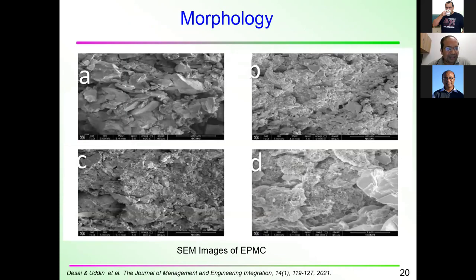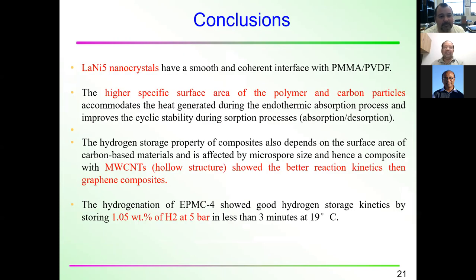Does anybody have any questions up to now? I think we're good. Okay, then this is the conclusion. Actually, I am not showing many results here, just giving some brief idea, some knowledge about it. I used lanthanum nickel nano crystal structure, and from the SEM images, I did some other characterization processes that I'm not showing here. It makes a good interface with the polymer, and the higher surface area of the polymer and carbon-based particles substantially increases the cyclic stability during the charging and discharging process for hydrogen charging and hydrogen releasing.